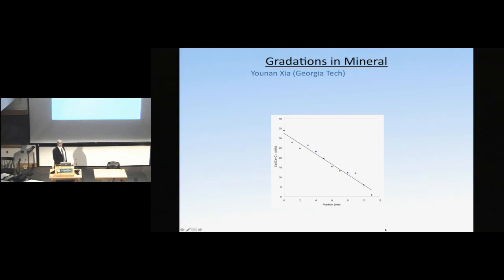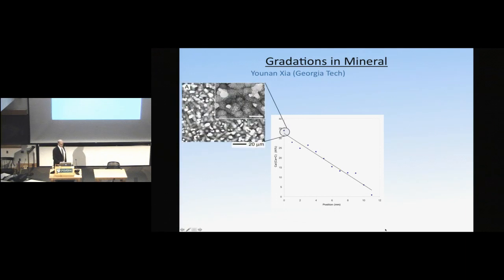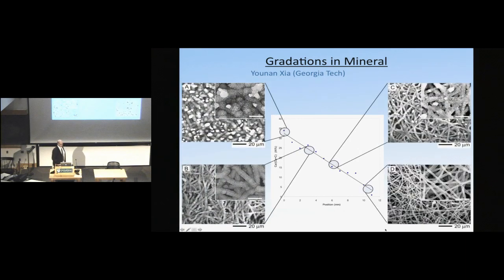And so we're working with Younan Xia, who's now at Georgia Tech, to create first PLGA scaffolds. PLGA is a polymer that's FDA approved and is biodegradable, that replicate the spatial orientation distributions and spatial mineral distributions that are observed in vivo. And Younan has developed a very, very elegant technology to be able to do this. It gives very good control of the degree of mineralization, all the way from unmineralized to very highly mineralized, although we're working on some of these structures and what they should be.